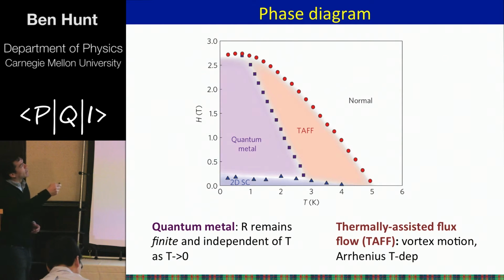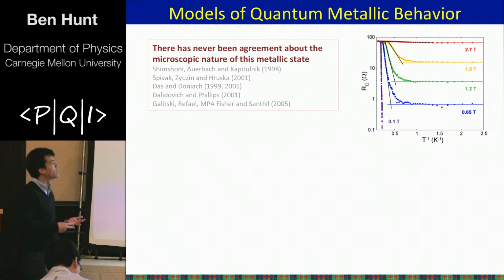So let's go back. I had mentioned that there's never been really agreement about the microscopic nature of this metallic phase that we see. The new ingredients that we've thrown in the mix are that we see it in a very, very clean superconductor, and that we observe this power law behavior. Okay? So there's sort of two prominent models that have come to the fore from these various theories.